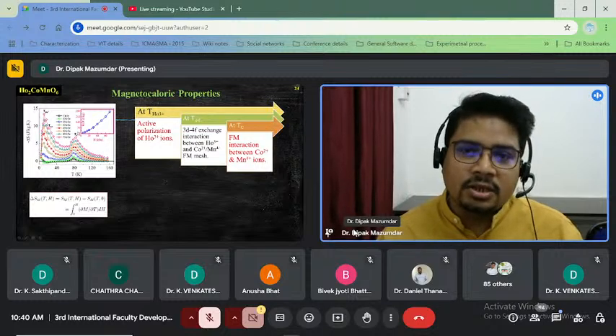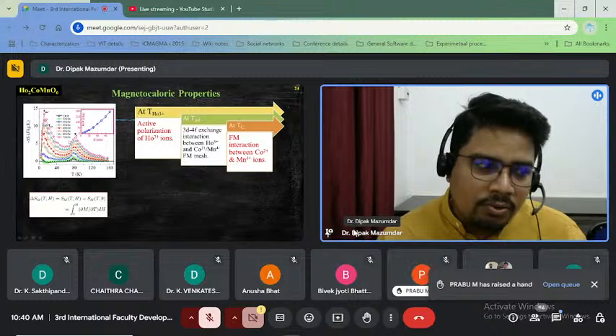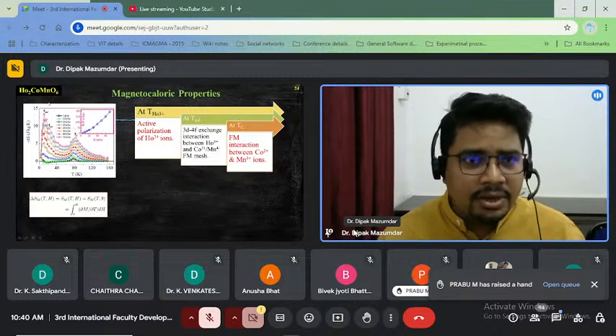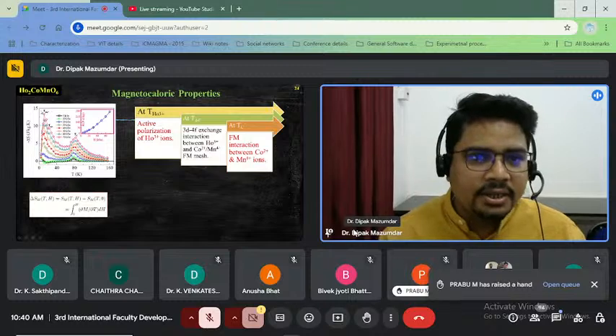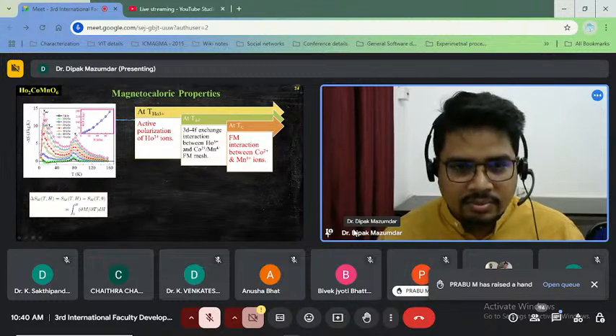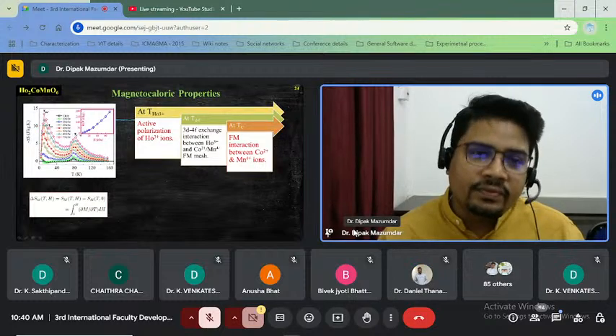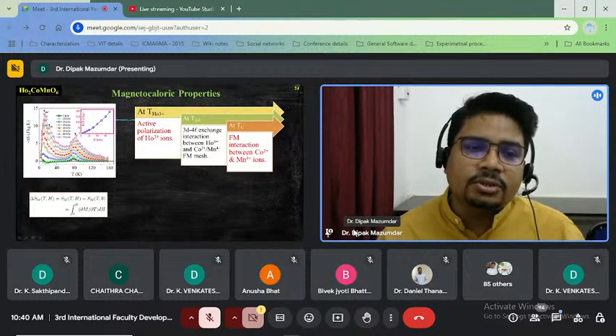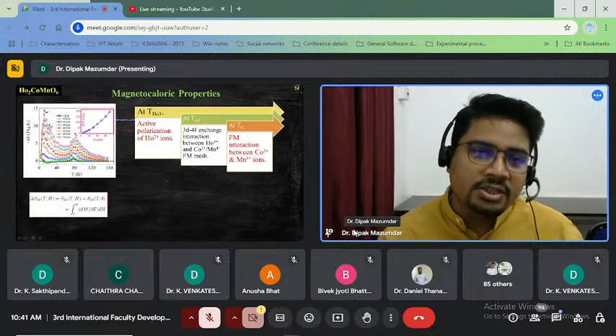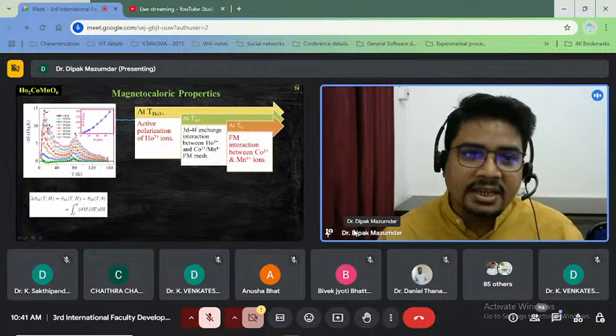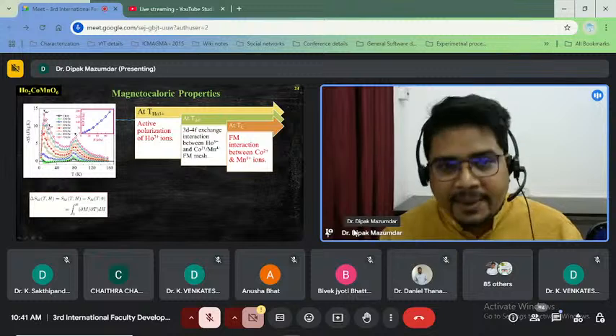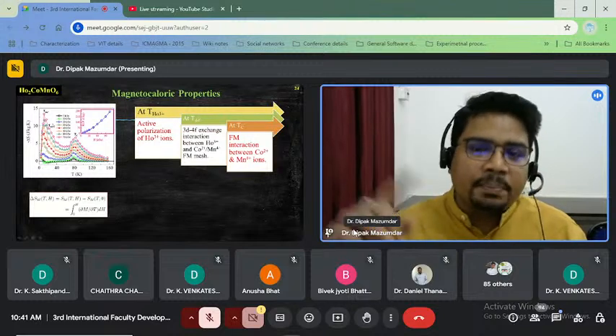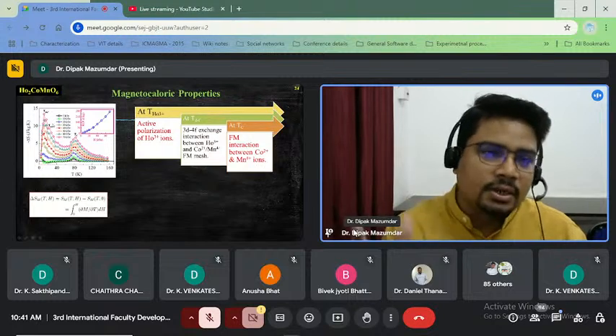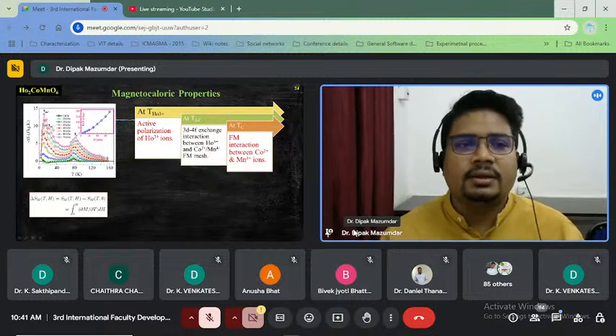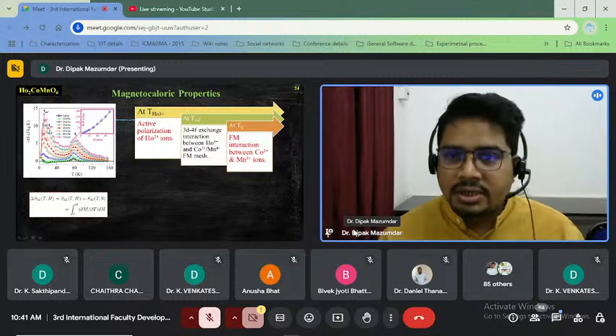So these three transitions show us how the rare earth ions orient independently. Then after, the transition metal ions also orient ferromagnetically, and there is an interconnection between these two as a 3d-4f exchange interaction. This also shows a signature in the magnetocaloric effect, and this signature is hidden in our temperature dependence of magnetization data. Although we get a peak, we can't justify what the peak is for. So from this graph, we can justify that this arises due to the 3d-4f exchange interactions.